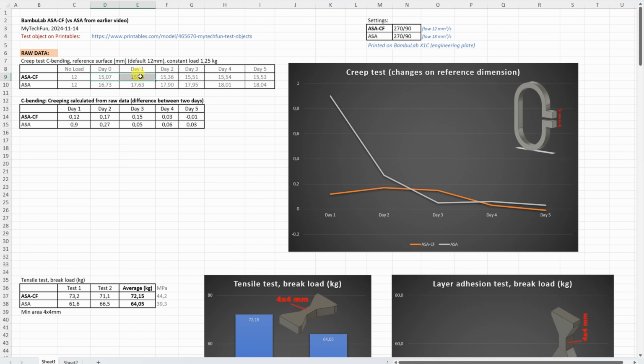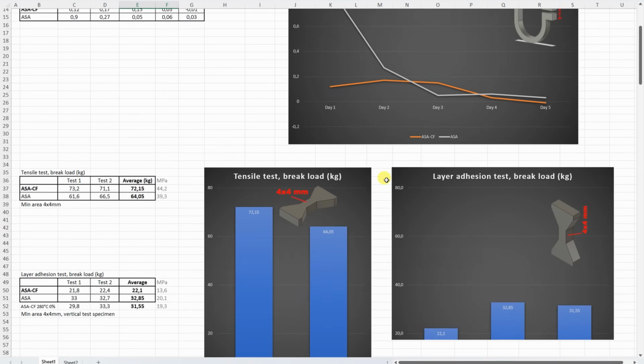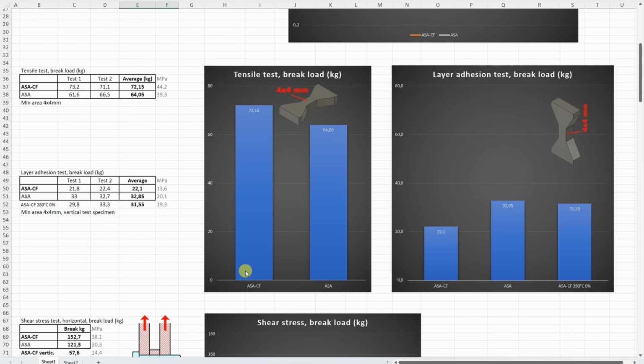And this is the distance between two reference surfaces, but what we need is the difference between 2 days. And we can see that the ASA-CF stopped with creeping even on the first day, until the ASA stopped with this deformation under this constant load maybe after 2nd day only. On a tensile test, the ASA-CF is slightly better, but the difference is not big. On the layer adhesion test, in first attempt, the ASA-CF is very weak, and this is what will be added to that summary table for my Patreon supporters, because it was printed with default settings. If I raised the print temperature and completely disabled the part cooling, then I got very similar results like with the ASA.